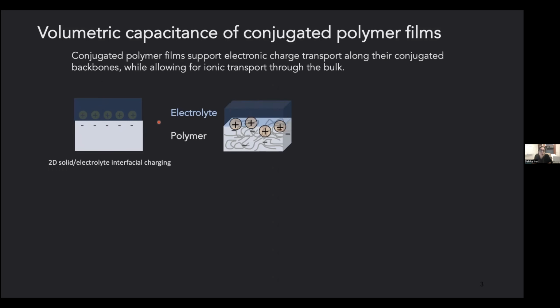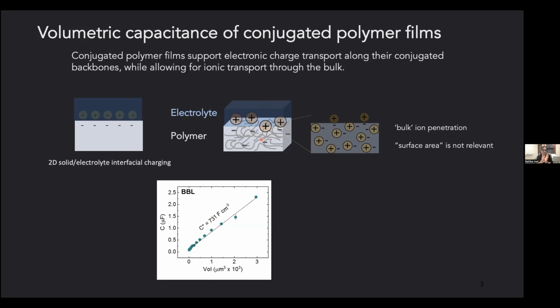When you do the same thing in a conjugated polymer film, the situation changes because these polymers, some of them, can uptake these ions into their volume and couple with electrons throughout the bulk of the film. So instead of limiting the charging, the electron or hole generation, at this interface, because the material has a certain porosity and affinity to these ionic charges, you can have electronic charge generation throughout the whole bulk of the film. So they do support electronic charge transport along the conjugated backbone, as well as allowing for ionic charge transport through their bulk. So this means as we increase, for instance, the size of this polymer film that we make in the electronic device, you do get a higher capacitance, and this capacitance scales linearly with the volume of the film.